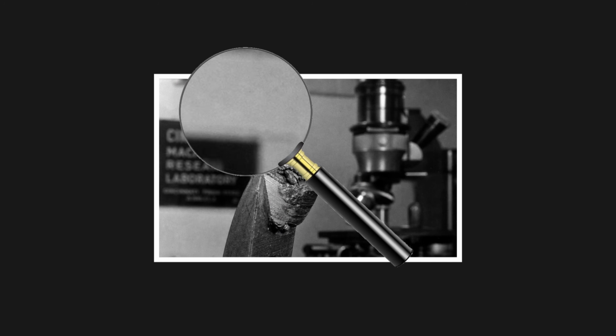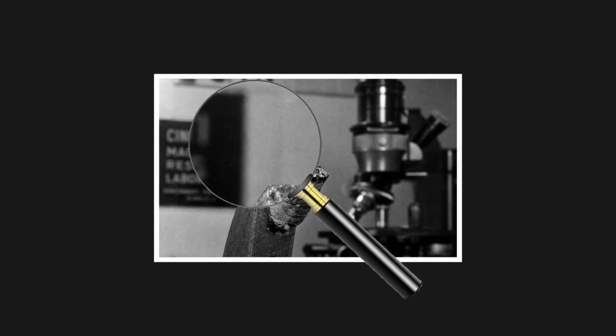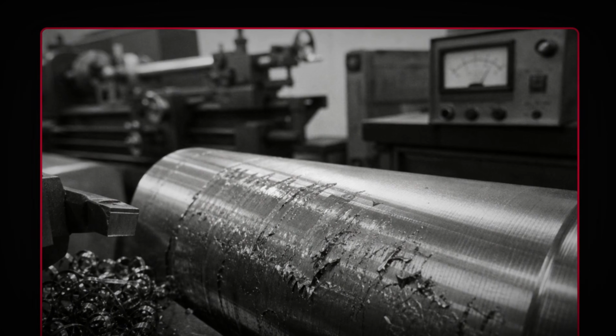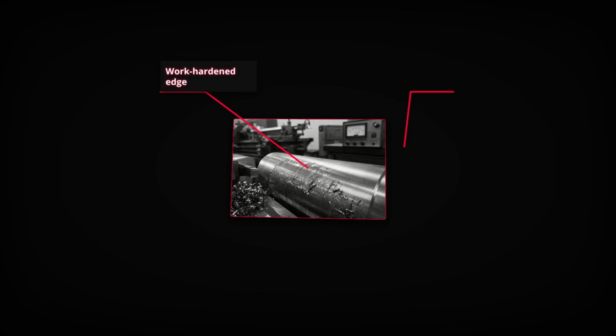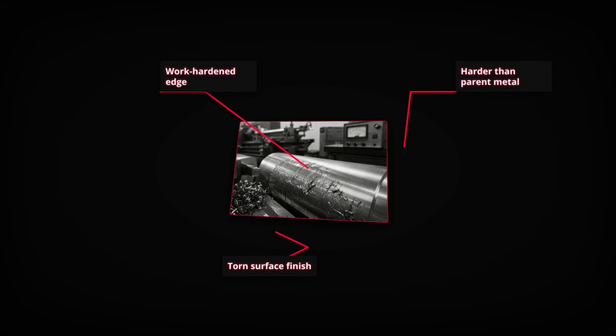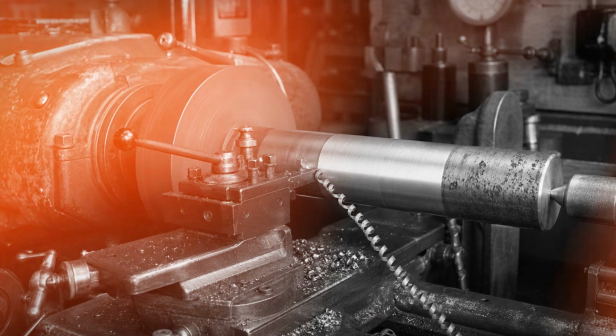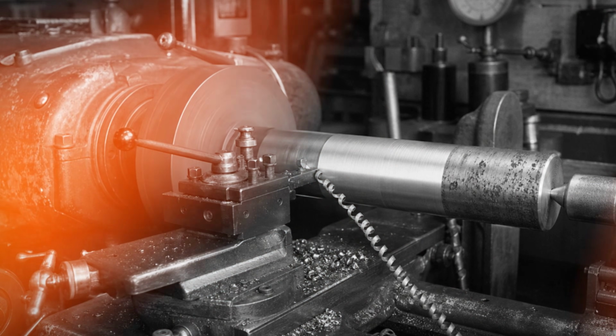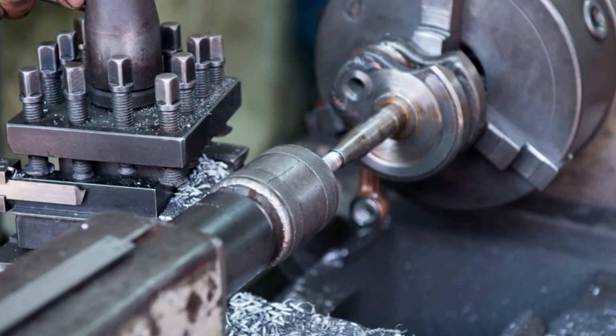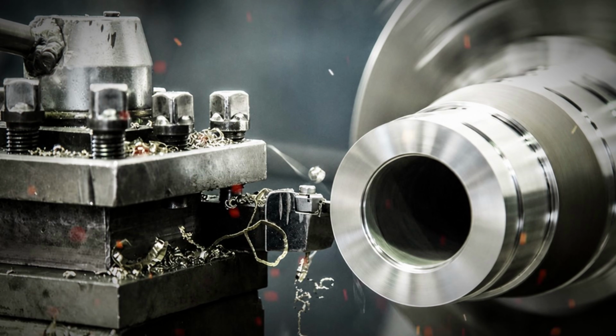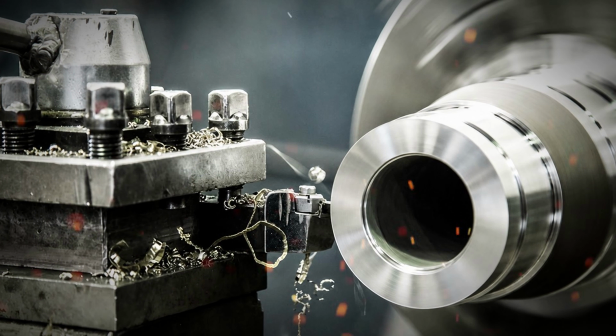The frozen chips exposed the machinist's oldest enemy, the built-up edge. Work material cold welding to the tool tip at moderate speeds. Work hardening until it is harder than the parent metal, then tearing away and taking the finish with it. The cure ran the same direction the materials were already pushing. More speed, slicker surfaces. Run fast enough and the metal is too hot to stick.